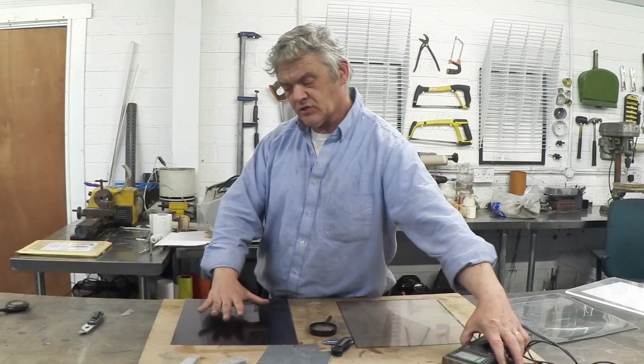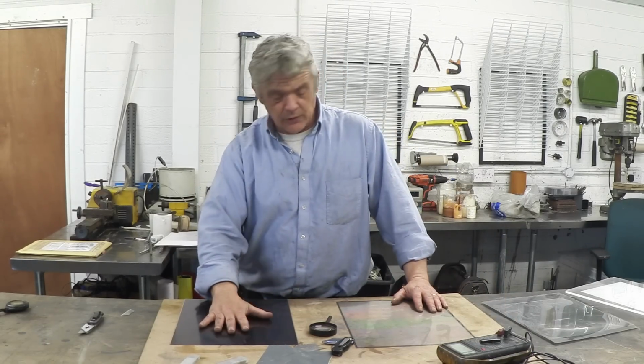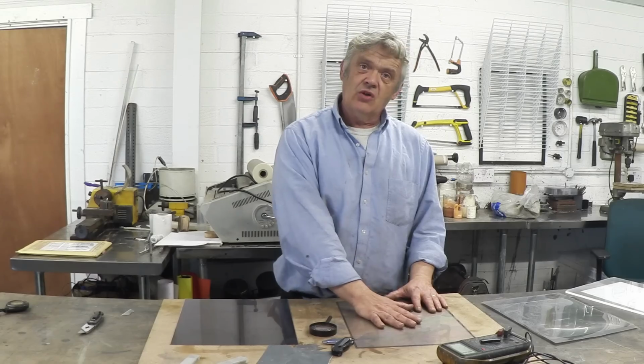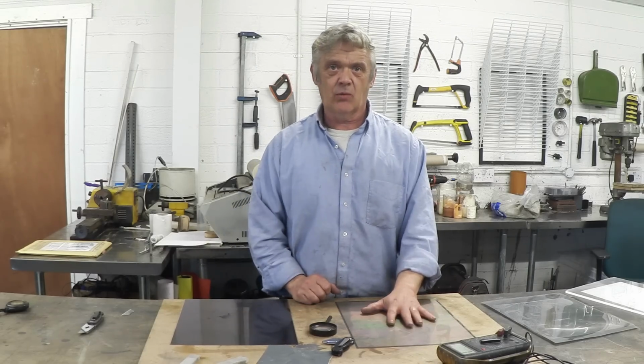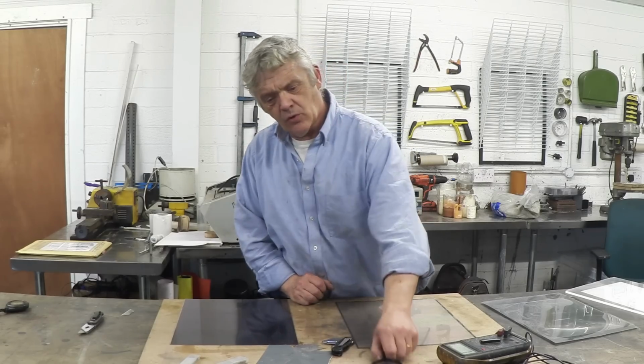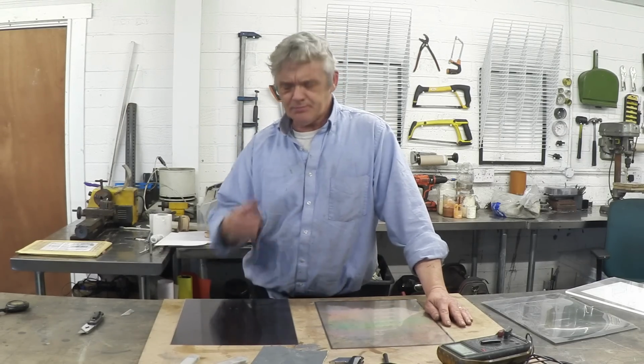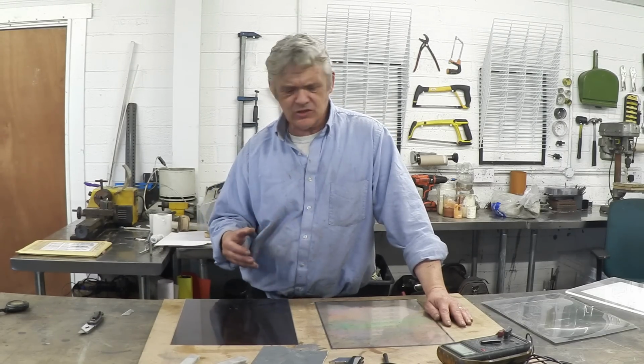That's because the indium tin oxide, which is a big layer on here, is sitting on the top. The indium tin oxide on here is sitting underneath the polyimide. There's much, much more ITO on this one than there is on this clear one. So it's a question of how to reclaim it. Now, there's an awful lot of work going on reclaiming this stuff because indium is scarce and getting stupidly expensive. What they normally do is grind these up. They grind them up and then they give them a wash and use a chemical method to actually collect them. And we're going to do something very similar.